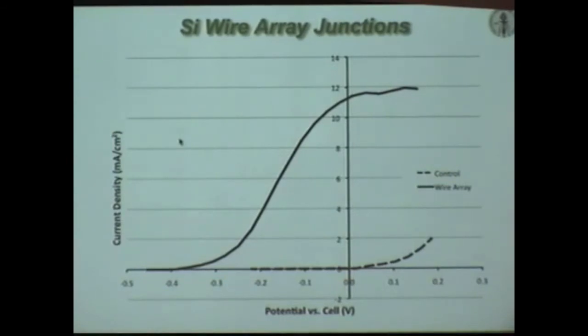We get about 450. This is a current voltage curve in a liquid junction of those rods. A single crystal of silicon, expensively purified under these conditions, would give us 500 millivolts open circuit. We're at 450. It would give us 30 milliamps per centimeter squared. We only get 12 now, but that's because we only fill 5% of the optical filling plane at normal incidence. We've got to do better than that. And we still have a shunt left behind. That shunt, we believe, is due to the residual gold on the side walls that we're furiously etching off right now. So in principle, this works.